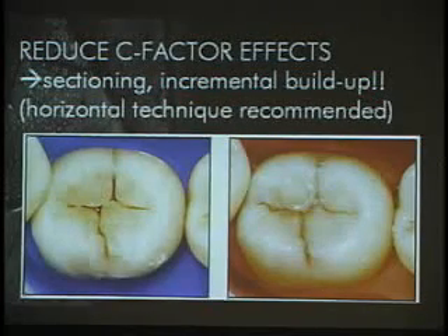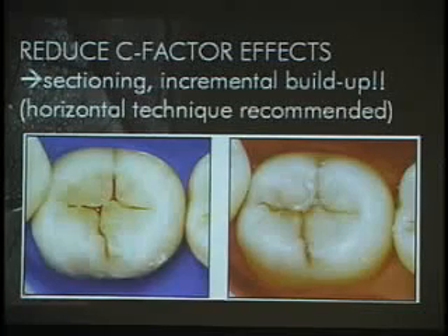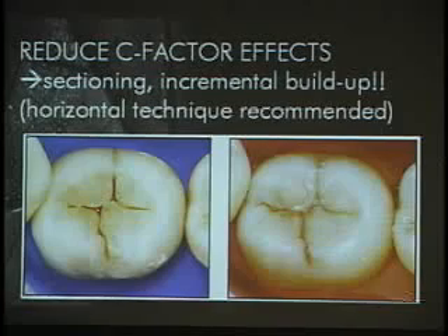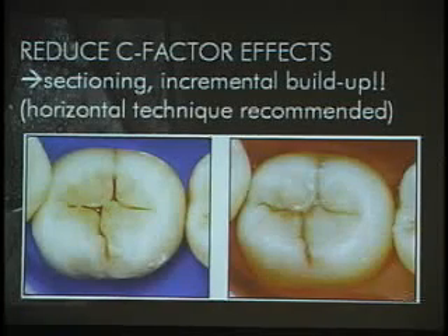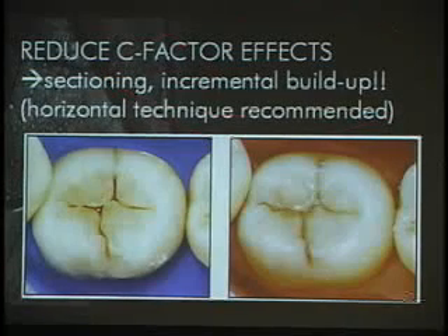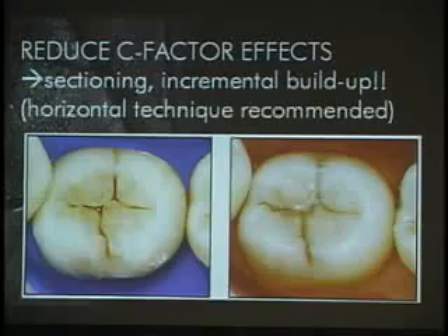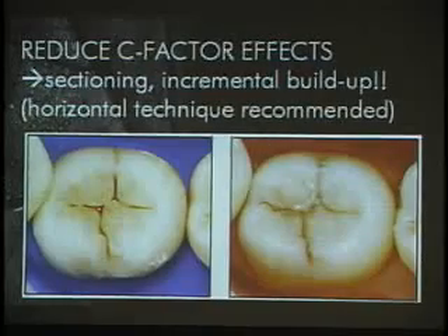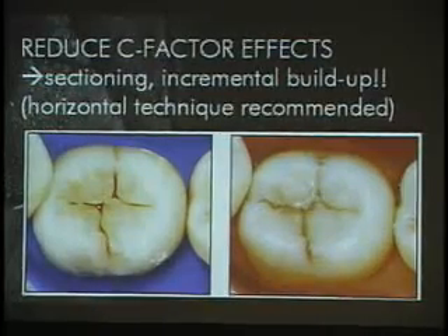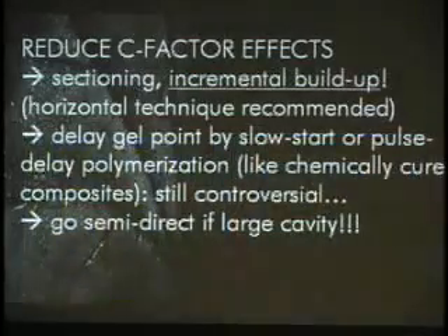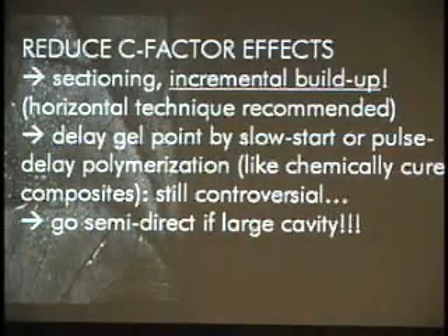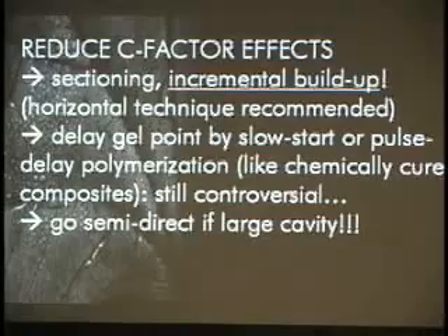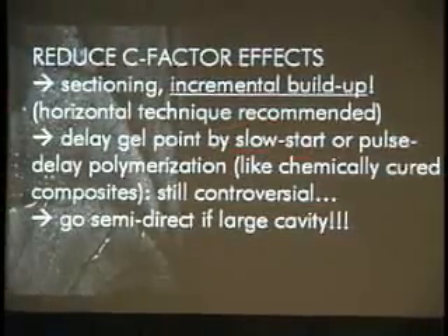A bulk, we should not fill a cavity in bulk. That is going to create more shrinkage and more problems than if we do incremental building and we segment the cavity in smaller increments, and there is less shrinkage. Also, researchers agree more or less that a horizontal layering technique in 1 millimeter increments is working very well.